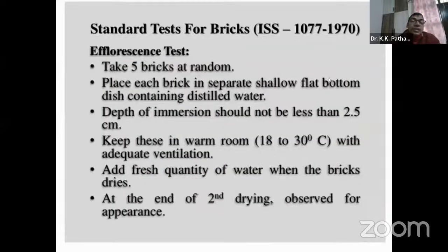Another thing is called efflorescence, where you can see white layers deposited on the brick when they absorb the water, because of the salt. That is very common in our areas in UP. I've been there in some projects, and we see that a lot of this problem is there. And this continuously will keep your building damp. So we have to remove those types of brick before using them. We should discard them if efflorescence is there.